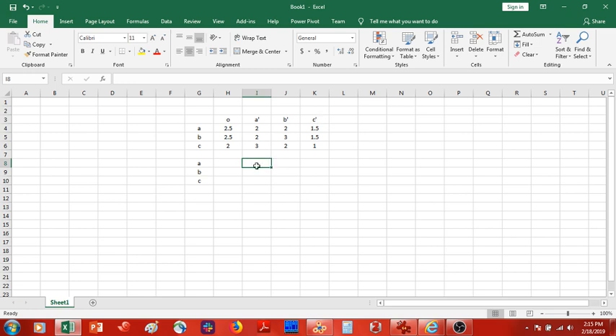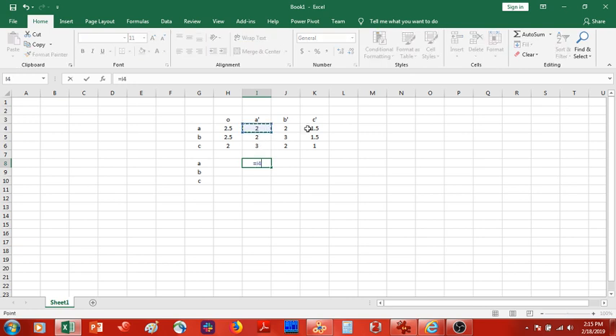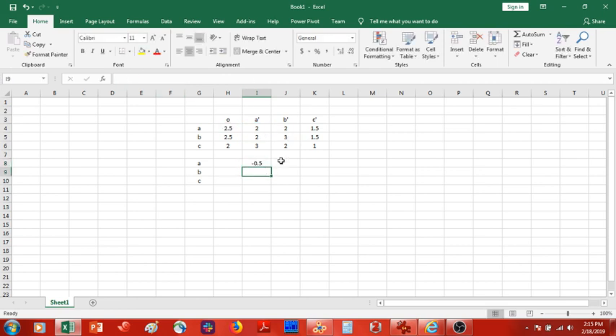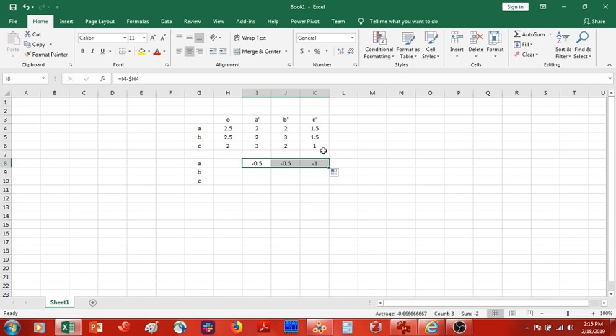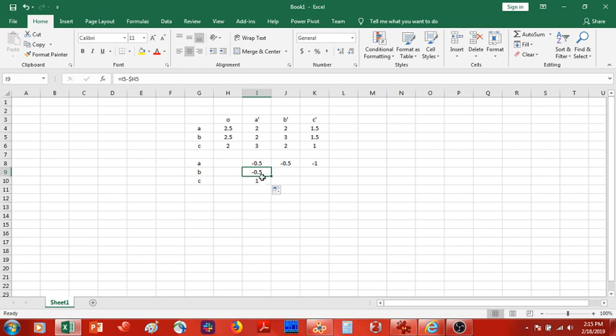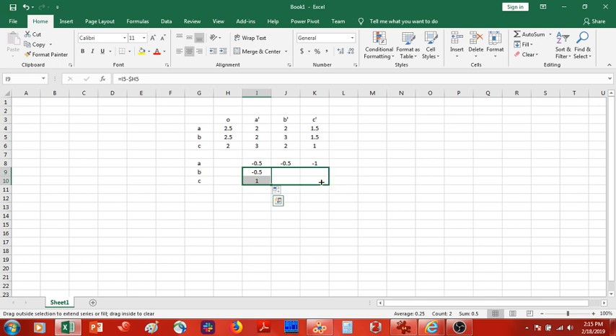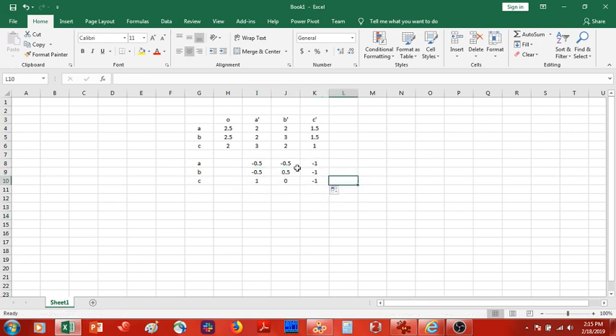Now what I need to do is define these A prime, B prime, C prime with respect to the origin, or relative to the origin. All I do is I take the value of one of these distances, in this case it'd be the cell I4, and I subtract the origin. Here you're going to want to put a dollar sign. Then I move it over like that, so you can see it's just this column minus this column. These are now the relative coordinates of the basis vectors for my new unit cell with respect to the origin. Now what I'm going to do is use this as a transformation matrix from my old unit cell to my new unit cell.